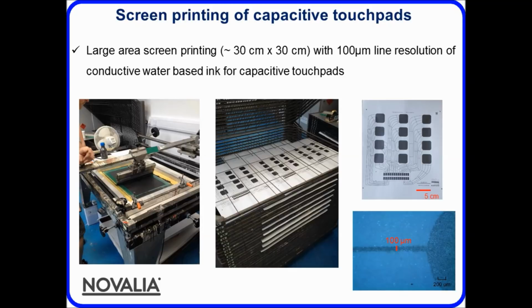So here we went to a local screen printing press and produced quite a few litres of ink, and we were able to print a few hundred of these posters, which are A3 sized. We can see here we have resolution of the lines down to around 100 microns. So that was just one demonstration that we can make functional posters and print them on paper, which can obviously be very cheap and recycled.